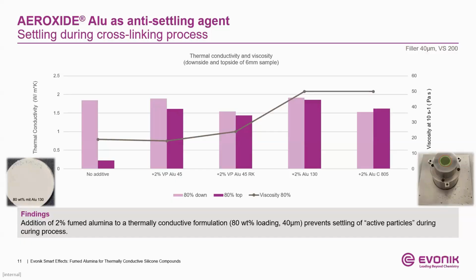And again, this all allows the fumed alumina, even this 2% addition low loading level, gives you those suspension benefits while in most cases maintaining a very workable viscosity for your thermally conductive silicone compound.